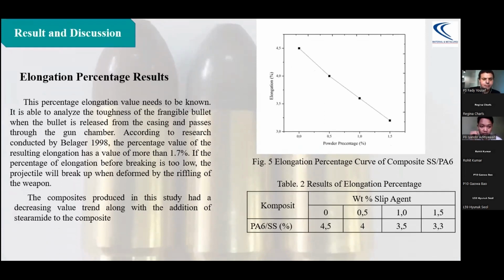Then the elongation percentage ratio. This percentage elongation value needs to be known. It is able to analyze the toughness of the frangible bullet when the bullet is released from the casing and passes through the gun chamber. According to the research conducted by Belanger, the percentage value of the resulting elongation has a value more than 1.7%. If the percentage of elongation before breaking is too low, the projectile will break up when deformed by the rifling of the weapon. The composite produced in this study had a decreasing value trend along with the addition of stearamide to the composite. You can see in the curve of the composite elongation percentage, there is a decreased value of the elongation percentage.